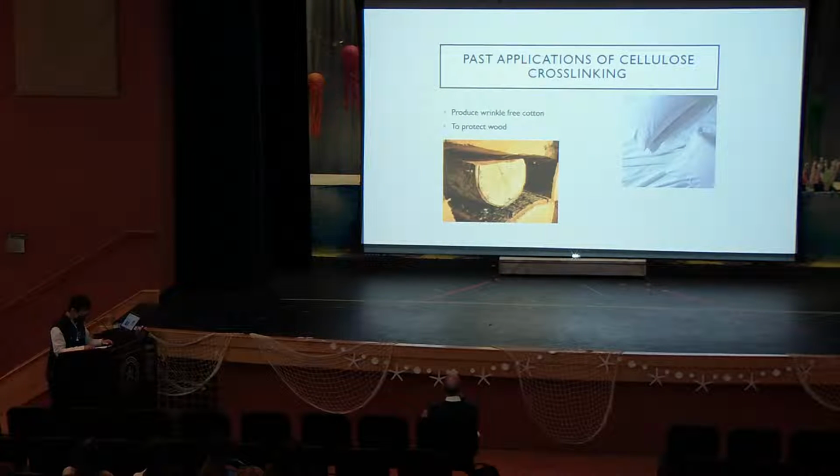Another application of cellulose cross-linking is to use it to protect wood, which also happens to be made of primarily cellulose fibers. The wood is cross-linked by DMDHEU at temperatures above 100 degrees Celsius, and due to its two methylol groups, which can react under water separation with OH groups of the wood and with itself, bridges are formed between adjacent cellulose molecules. The product from this process is on sale under the name Belmadur. It has the expected dimensional stability, especially for dimensional components such as windows and exterior doors, and durability up to the best class 1.